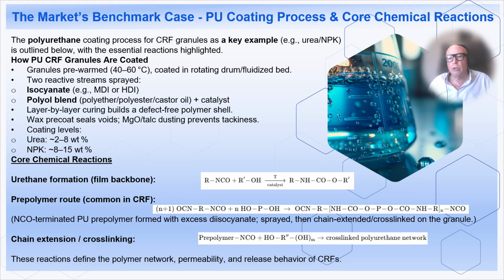The prepolymer route is common in CRF production. You form an NCO-terminated polyurethane prepolymer with excess diisocyanate, spray it onto granules, then chain extend and cross-link it on the granule surface. This layer-by-layer curing builds defect-free polymer shells. Coating levels vary significantly. Urea typically needs only 2 to 8% by weight, while NPK granules require 8 to 15% coating to achieve equivalent performance. The granule chemistry affects how much polymer protection you need.